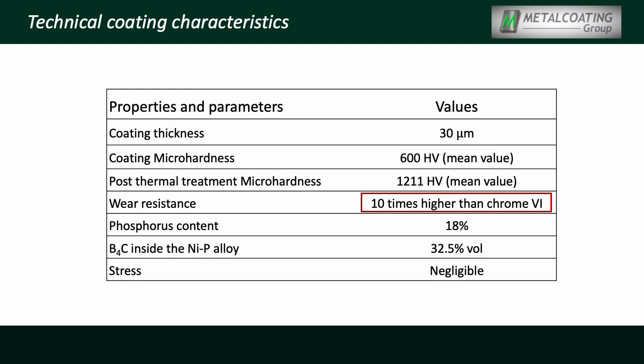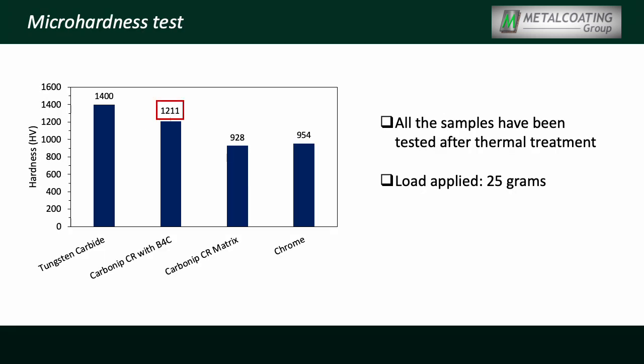In this slide some mechanical properties are shown: the microhardness value before and after the thermal treatment, and the percent in weight of phosphorus and in volume of boron carbide. The following slide shows a comparison among the Carbonip and other coatings. Thermal treatment was carried out before testing. The hardness of the Carbonip is in between carbide and chrome.